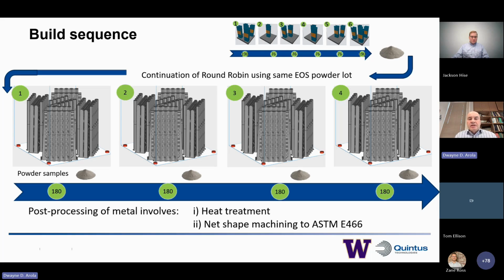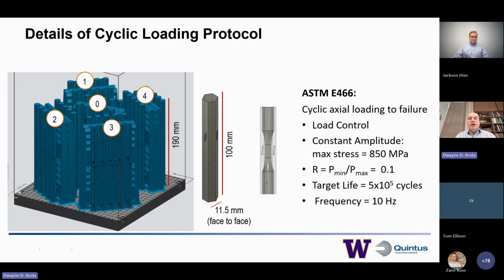And so after receipt, again, I talked about the heat treatment and, of course, the net shape processing, which was conducted in order to be able to meet the standard, which is defined by E466. So just for those of you who are fatigue individuals, we performed all of our fatigue testing according to E466. That's cyclic axially loading to failure.